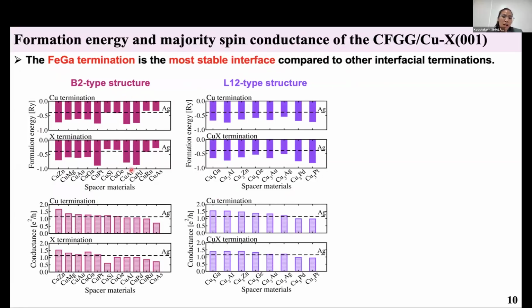So the results are compared with the Ag spacer and indicated by the black dashed line. The first column is the result for the B2 type structure with copper and X termination, and the second column is the result for the L12 type structure with copper and copper X termination. For the formation energy, a more negative formation energy indicates a greater stability.